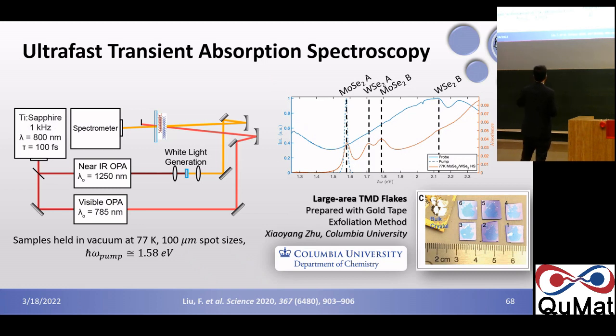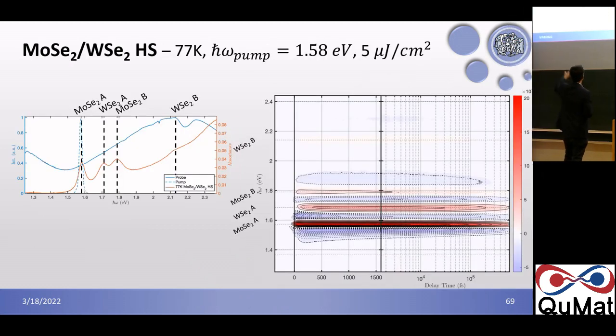We can do much more sophisticated experiments. In particular, what we can do is again a pump probe, but outside the microscope, where we can have a really broadband probe that covers simultaneously all the excitonic transitions. Before we only covered one color. So now we are pumping in resonance with the A exciton of MoSe2. And here we see all the 4 excitons, even the B exciton of WSe2. We can see the bleaching of all these 4 excitons. And we see quite nicely, even from this data, that the A and B exciton of MoSe2 rise nearly instantaneously with our pump, while the A exciton of WSe2 is clearly delayed by approximately 300 or 400 femtoseconds.